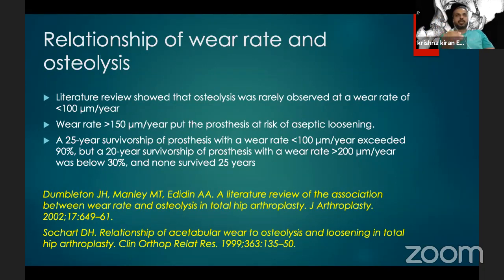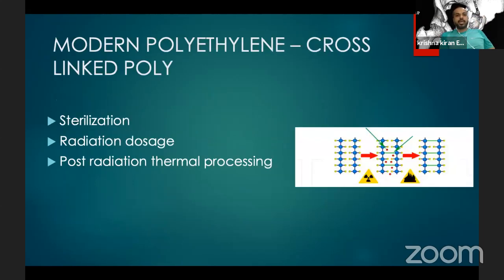So it is important to position your implants very well, to have better bearing couples, to have the optimal head size and optimal thickness of the polyethylene in order to minimize this osteolysis threshold that is seen with the polyethylene particles. Now, the modern polyethylene is the cross-linked polyethylene. It has eliminated a lot of problems related to the conventional polyethylene, where there is osteolysis related to the polyethylene wear particles. So we do not use any conventional polyethylene in modern total hip arthroplasty.